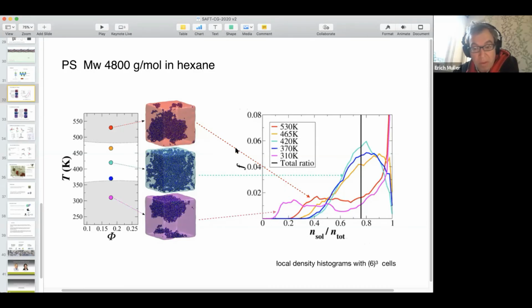So for example, for this red curve, what it says is that there is a certain composition associated with around 40% of the solvent in this case. And there is another peak, which corresponds, of course, to the pure solvent, which is these areas. So what we're doing is basically a histogram of the density distribution in one snapshot, averaged over many snapshots. This is molecular dynamics, so we just collect many of these snapshots and look at it.